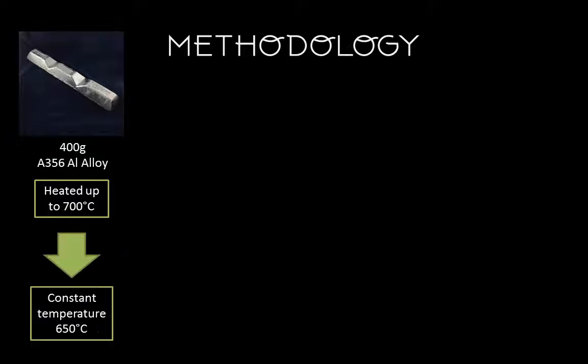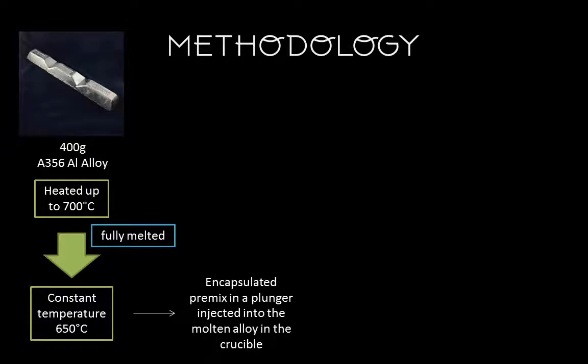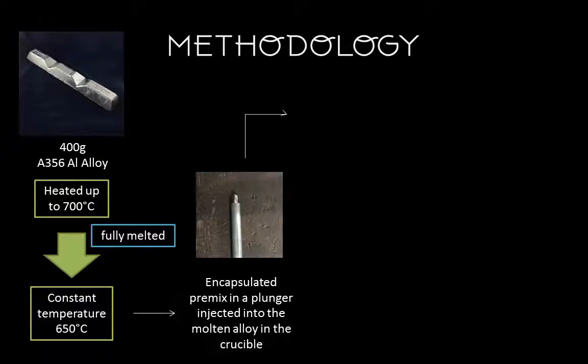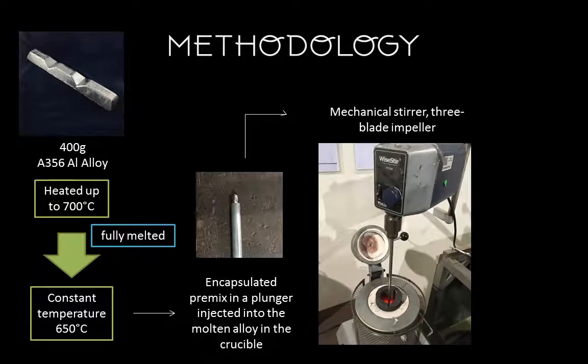The next step is to have 400 grams of A356 aluminium alloy heated up to 700 degrees Celsius before it is brought down to a constant temperature of 650 degrees Celsius. The reason for it to be heated up to 700 degrees Celsius is to ensure that it is fully melted. And the next step is to have the encapsulated premix put into a plunger and injected into the molten alloy in the crucible before it is mechanically stirred using a mechanical stirrer equipped with a 3-blade impeller at 500 rpm.